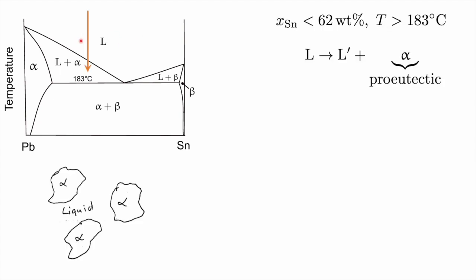So, supposing we take an alloy of this composition and allow the liquid to cool. So this alloy would have a concentration of tin which is less than eutectic, and the temperature is greater than the eutectic temperature of 183 degrees. So we are cooling this, and the first thing that happens is the precipitation of pro-eutectic alpha here. We call it pro-eutectic because it's before the eutectic temperature is reached. And these would be grains of alpha or dendrites of alpha forming in the liquid.